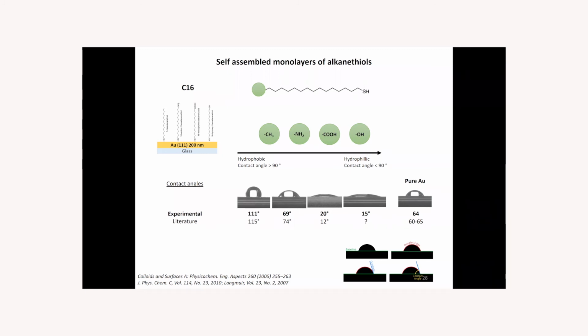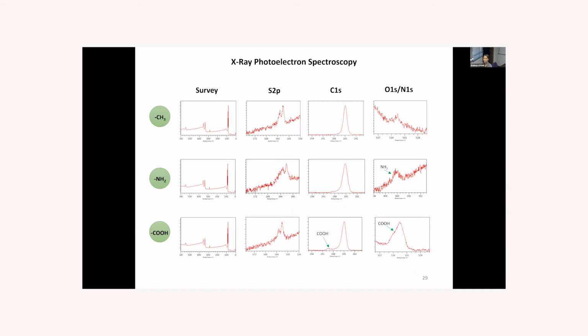We have measured, first of all, the contact angles of our formed monolayers, and our experimental results for contact angles are fitting well with the literature reported values. So we are quite confident our monolayers were well formed. We have also characterized the samples by X-ray photoelectron spectroscopy in order to see if we can see the right elements present on the surface. For the amino group, we could see the nitrogen peak, and for the carboxylated surface, we could see the expected features in the carbon peak and also in the oxygen peak. While for the methyl group, we have seen almost no oxygen.